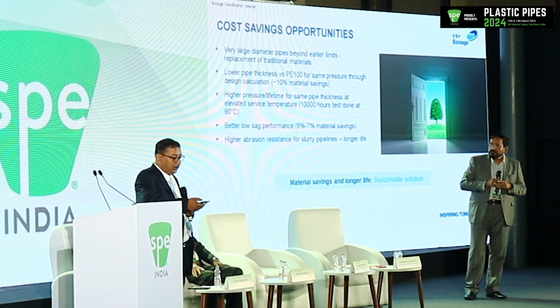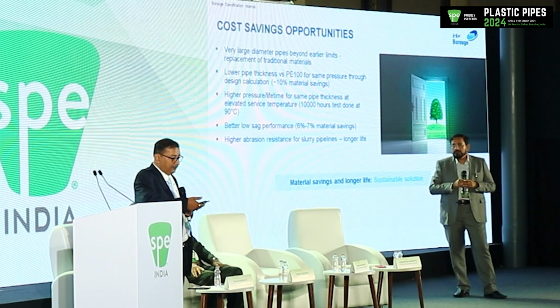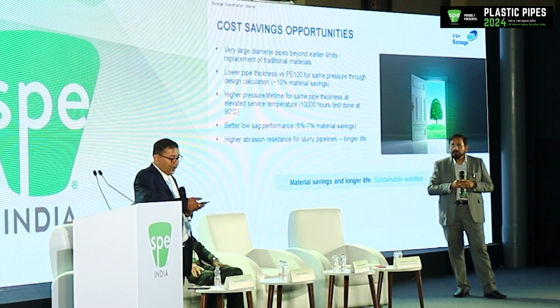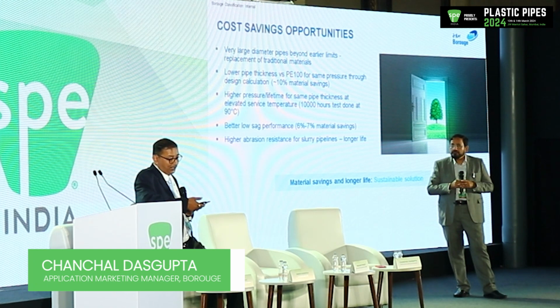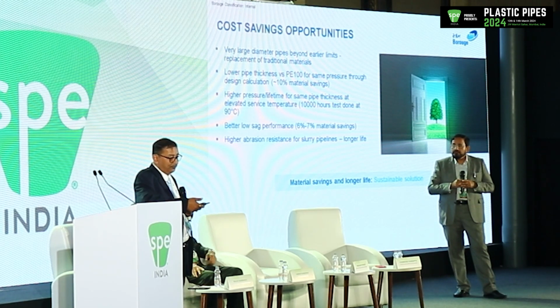So, summarizing the cost saving opportunities: very large diameter pipes beyond earlier limits, replacement of traditional materials, lower pipe thickness versus PE100 for the same pressure through design calculation, you can have about 10% material savings, higher pressure lifetime for the same pipe thickness at elevated service temperature, because we have done 10,000 hours test even at 90 degrees centigrade, which means higher lifetime. Better low sag performance can save you anything between 6 to 7% material savings, and higher abrasion resistance for slurry pipelines gives you longer life. So material savings and longer life, which means a sustainable solution, which is also the theme of this conference.